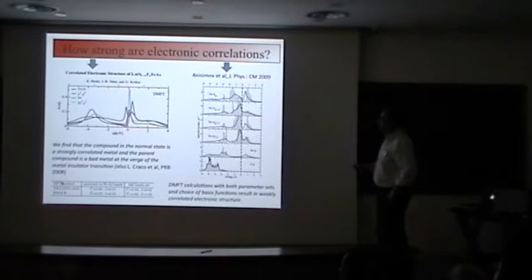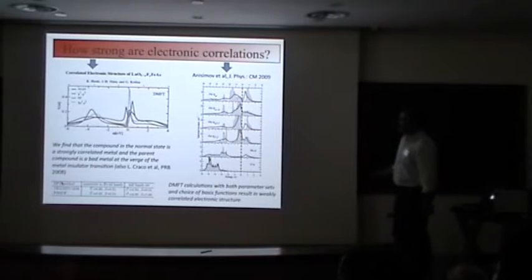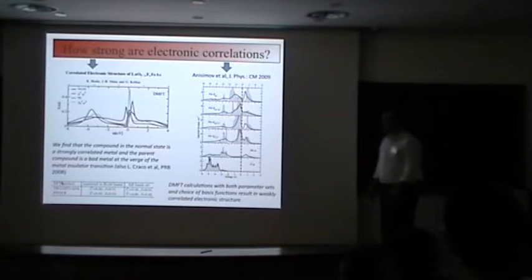The point is there were very different statements. One particular study from Craco considered the system to be a bad metal at the verge of a metal insulator transition, with values of U on the order of the bandwidth, maybe a little smaller. But another DMFT calculation concludes the opposite, that it's a weakly correlated electron structure with maybe a renormalization factor of 2.